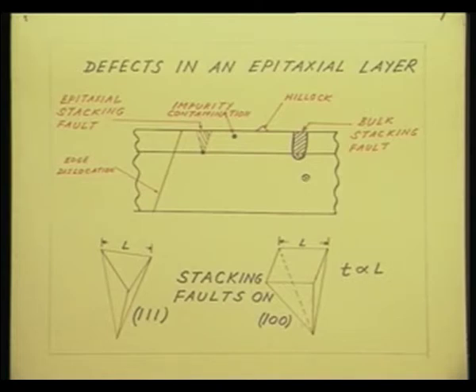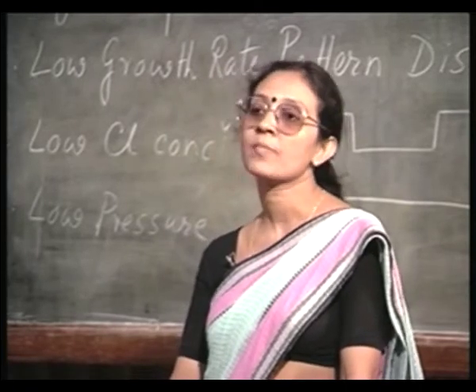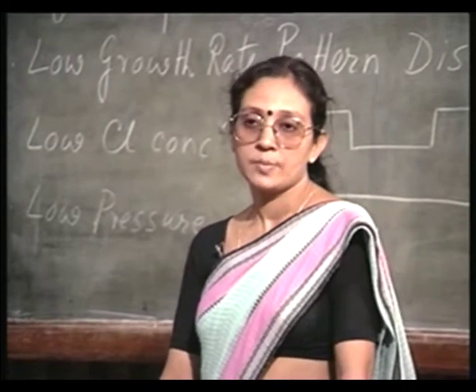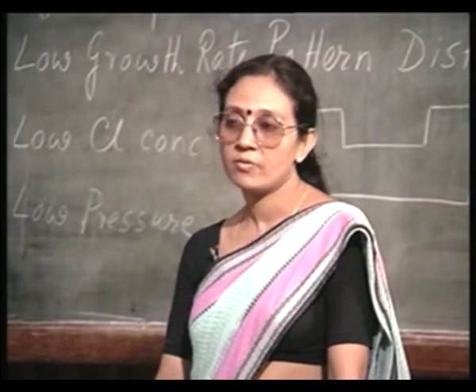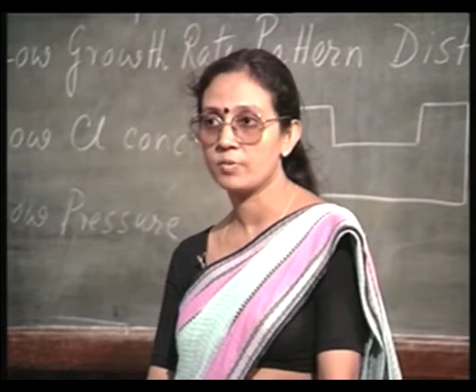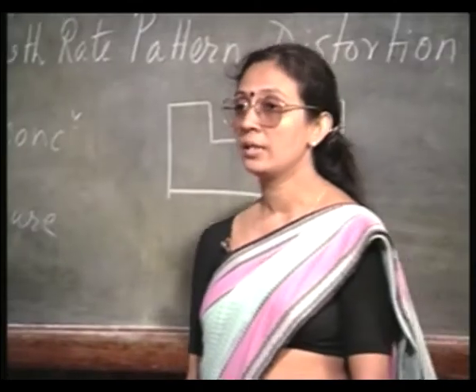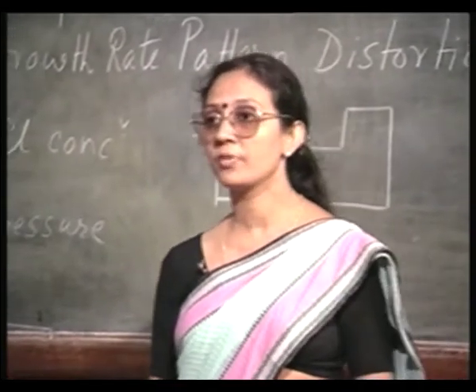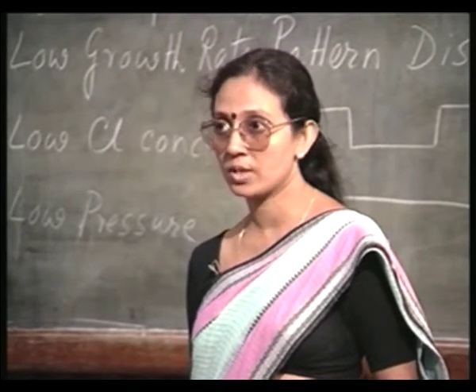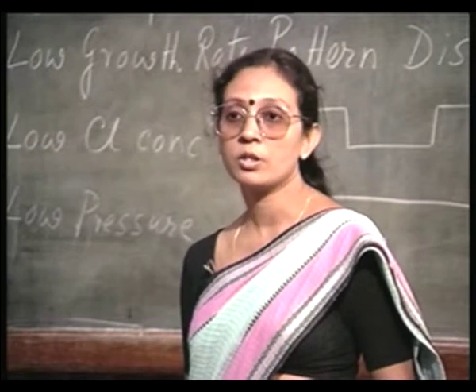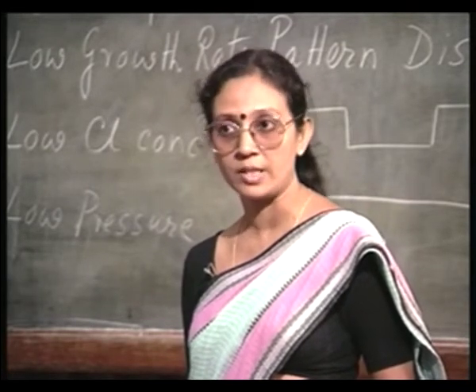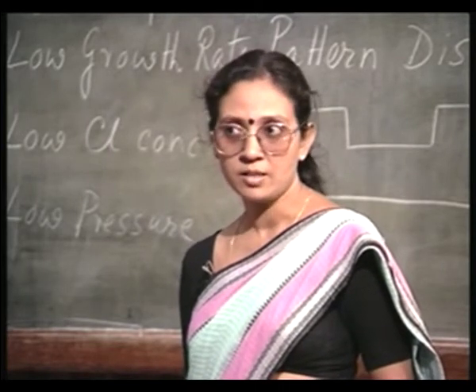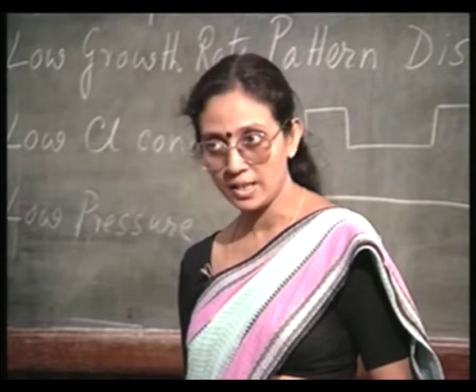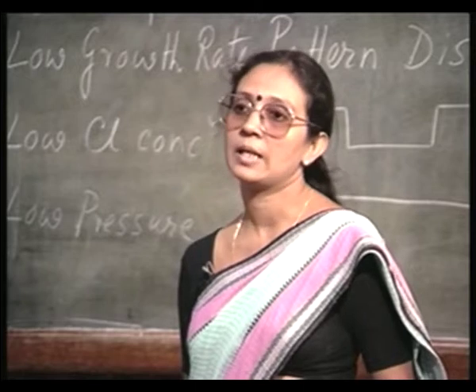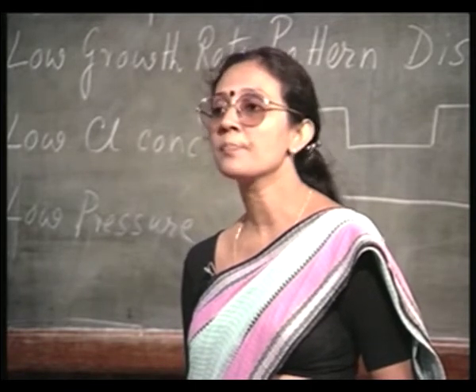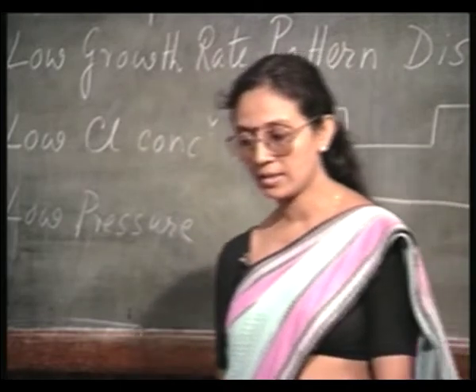And a proof of this, an experimental verification, is that the number of stacking faults is proportional to the effectiveness of the hydrogen cleaning of the silicon surface before epitaxy. Remember, before epitaxial growth there is an in situ cleaning step. In that step, first silicon is flushed in dry hydrogen at a high temperature, and this is done in order to reduce the surface, to remove all traces of native oxide. So, unless that is done, you will have a large number of stacking faults in the epitaxial region. So, it goes to prove that the stacking faults are closely associated with the traces of native oxide present on the silicon surface.